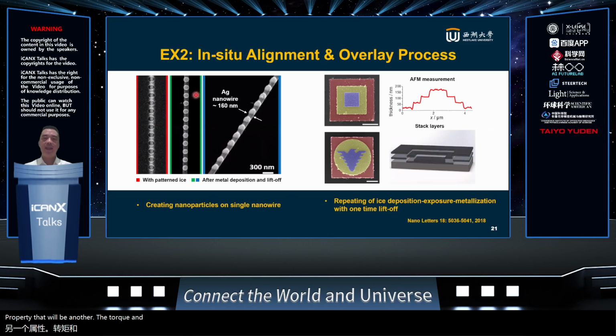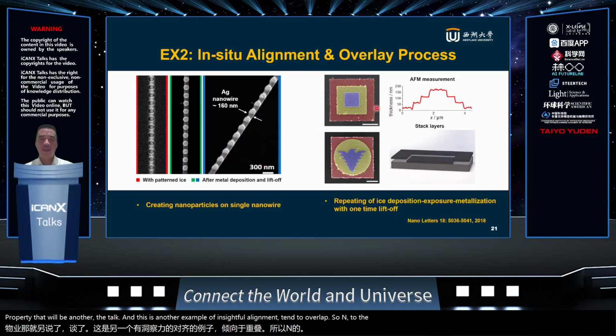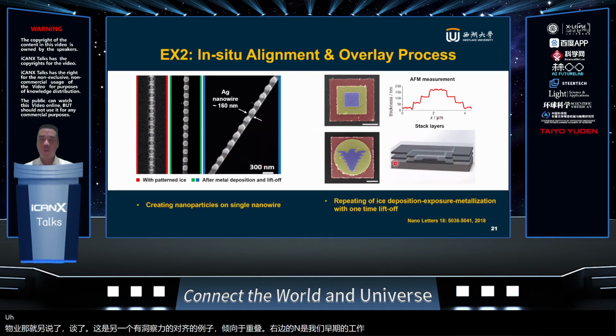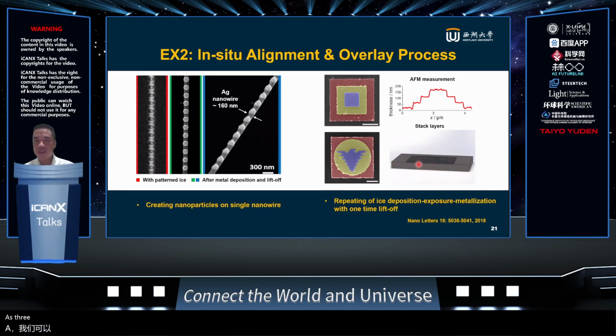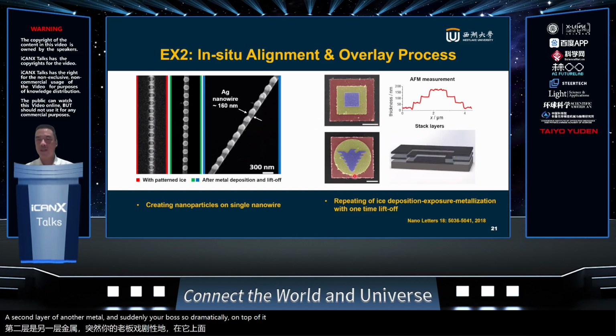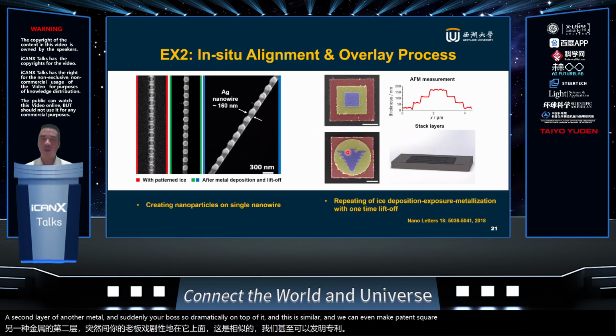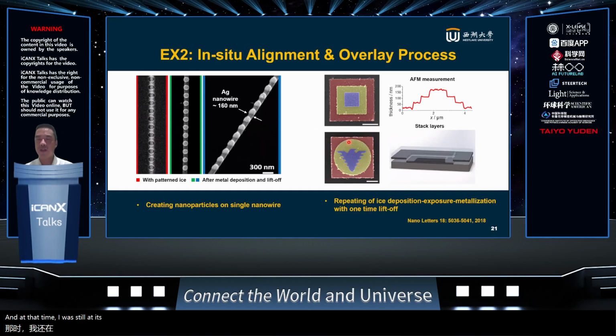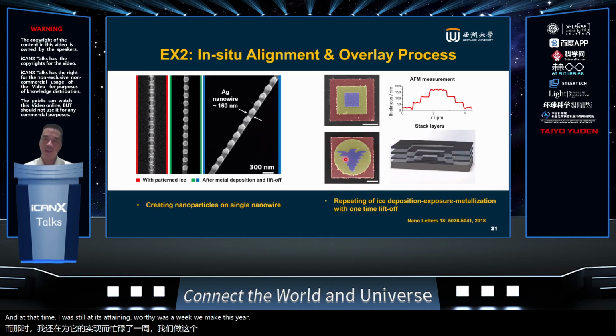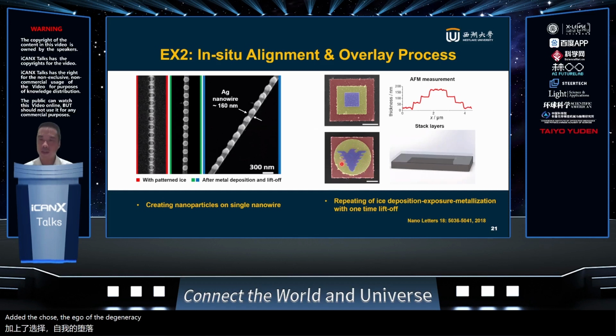And this is another example of in-situ alignment and overlay. To the right is our earlier work. We can make three stacking layers of device. For example, this one, a big square, a second layer of another metal, and a third layer of a third metal on top of it. This is similar, and we can even make patterns, squares, circles. At that time, I was still at Zhejiang University, so we made the Qiushi eagle of Zhejiang University on top of it. And this is all done in one single fabrication process.